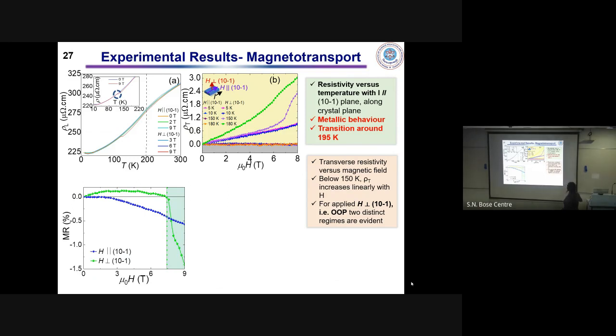However, for temperatures at or above 150 Kelvin, we can see two distinct regimes clearly evident. One is linear below a threshold magnetic field, and once we apply that threshold magnetic field, it increases suddenly, which might be attributed to an increment of the net magnetization because of the spin flop ordering of the antiferromagnetic moments under a magnetic field applied in the out-of-plane direction.